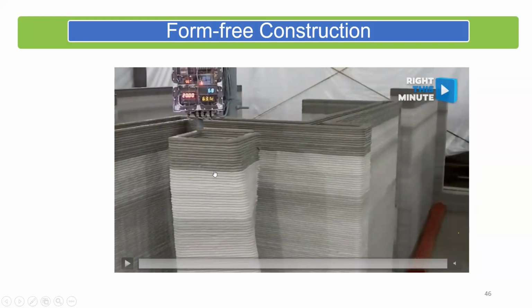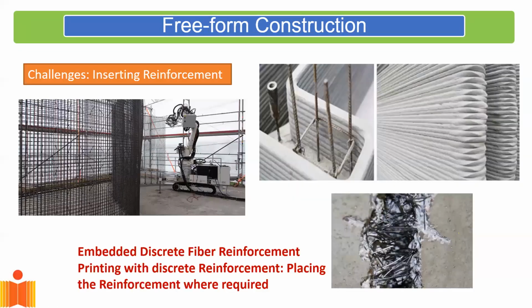And as you can see here, I add layers. So the layer that has been deposited before should be able to take the weight of additional layers. And these layers are still fresh, as you can see here, they're still wet. These layers have not yet set. So even the layers that have not yet set should be able to resist the weight of additional layers. The internal structure inside these has to develop to that point.